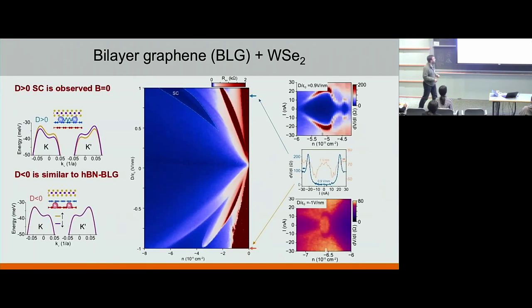Just as a record, here's one example where you see the superconducting gap. Moreover, in the case where you polarize the holes away from tungsten selenide, you reproduce some of the non-linearity and non-trivial features that are also present when you don't have tungsten selenide. So the moral of these couple of slides is that below displacement field less than 0, this behaves as just a bilayer graphene, which doesn't know anything about tungsten selenide, and above you have this huge superconducting pocket.